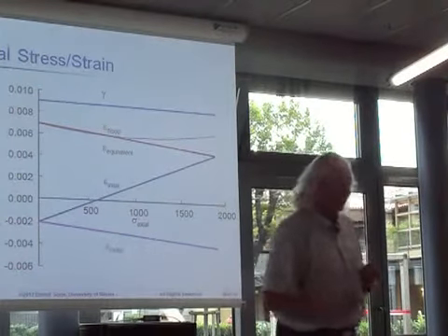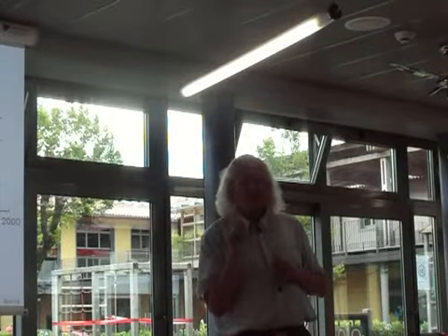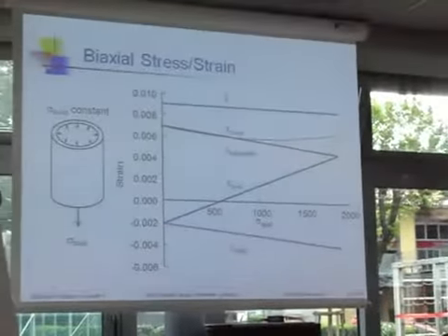Absolute nonsense. It's a true statement that the strains go down, but the strain alone is not the driving force for fatigue. You have to have stresses as well. Both become important. I'll come back to this and I'll show an example.